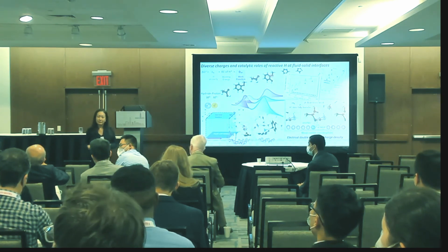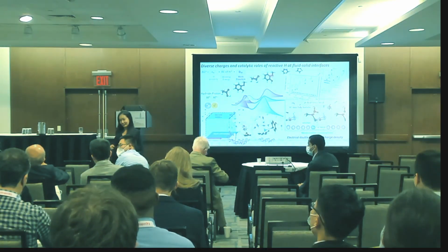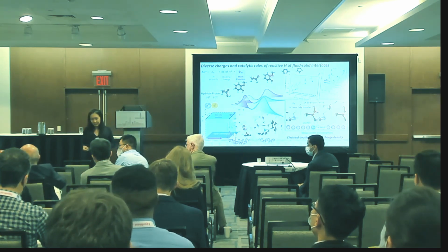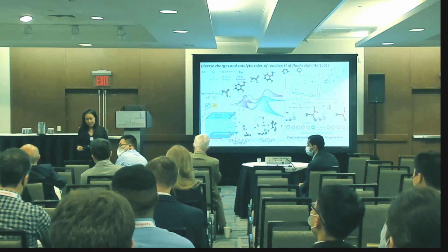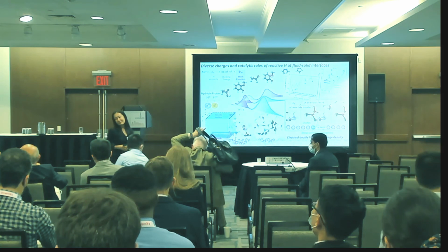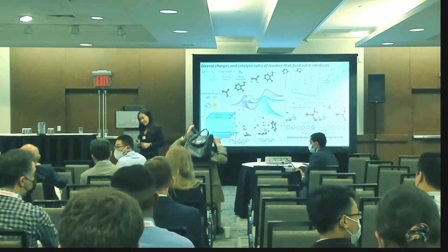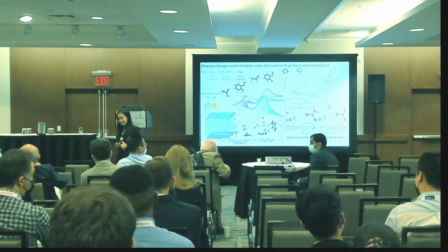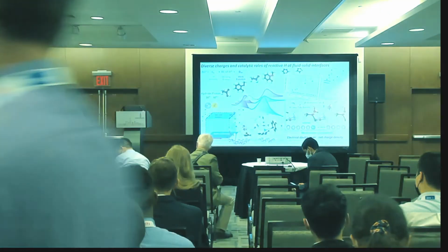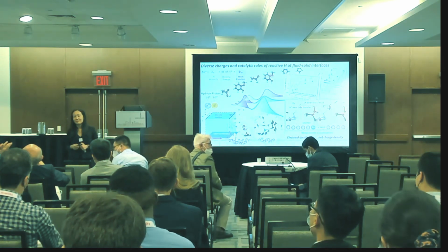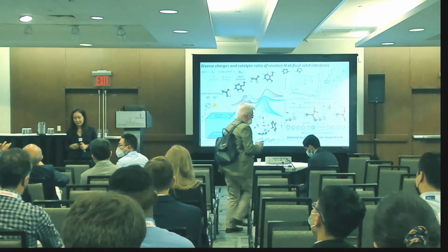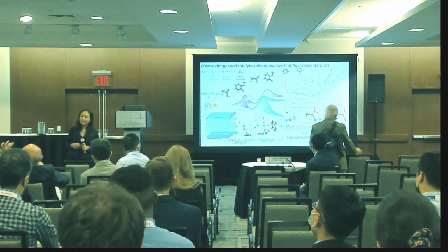The only thing is, if you look at the role of the metal when you want to close this thermodynamic cycle for the proton, the redox pair of a proton and hydronium ion, you do of course have to consider the electron affinity of your metal, and therefore you do change your band structure and your local Fermi level, because as you put it in water, you fix by your pH the Fermi level in the metal.